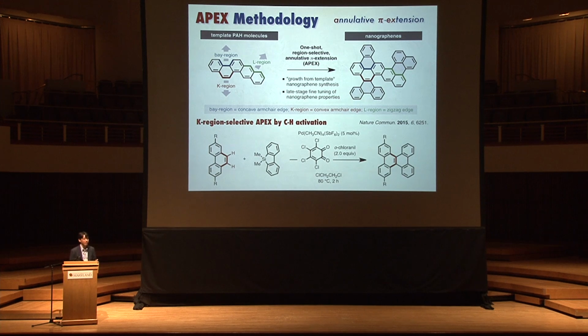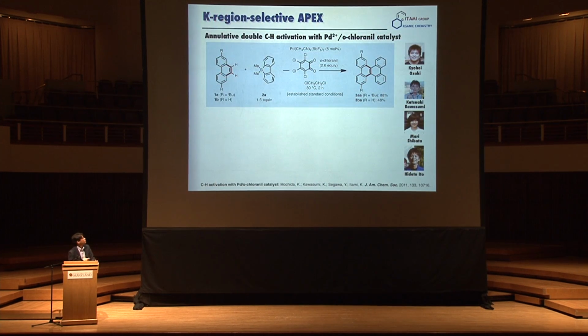It took us a lot of time, but now we were able to develop the first generation of such kind, the K-region-selective APEX by C-H activation. So we found that the palladium catalyst can do this. This is the final answer of our students. All you have to do is take PAH and mix it with a silicon-bridged aromatic, dibenzosilole for example. The catalyst is this cationic palladium(II), and we use o-chloranil as a ligand and an oxidant, which we have used since 2011. Under these conditions, the APEX reaction takes place selectively at the K region shown here to produce this one.